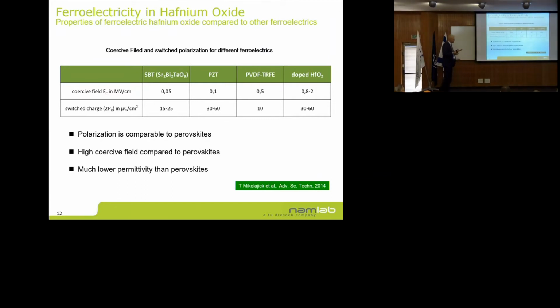Now, let's look at the parameters, and I want to bring two key points across from this table. If we compare the doped hafnium oxide with PZT or SBT or even PVDF-TrFE, we will see immediately that the coercive field is much higher. The polarization is in a similar ballpark, and not given in the table but stated here, the permittivity is much, much lower. We normally are used to call hafnium oxide a high-k material, but actually it's a low-k ferroelectric, and that'll be very important in what I will show you later on.